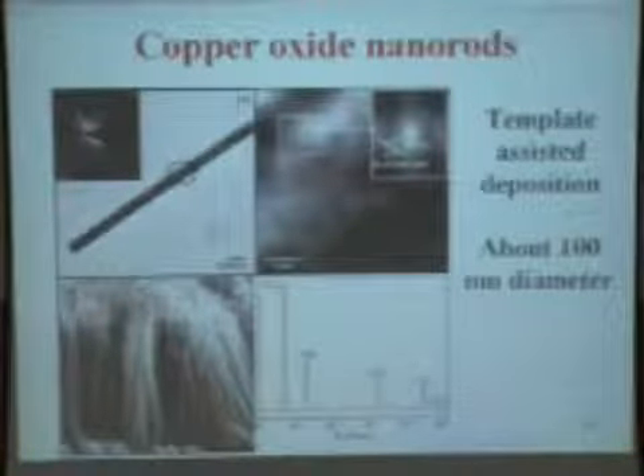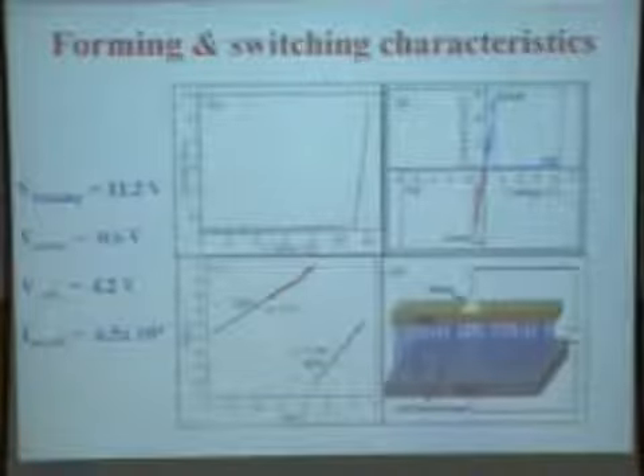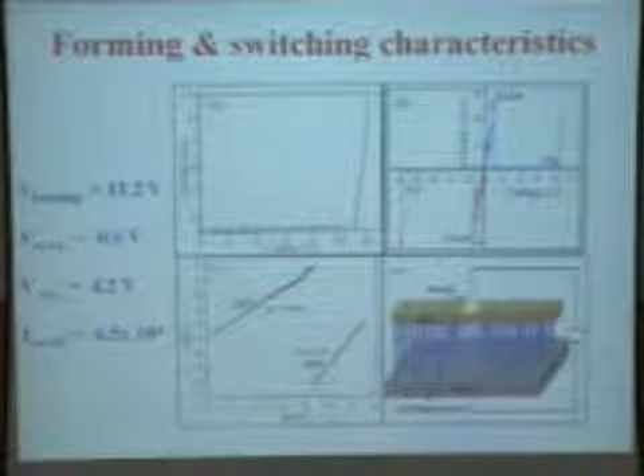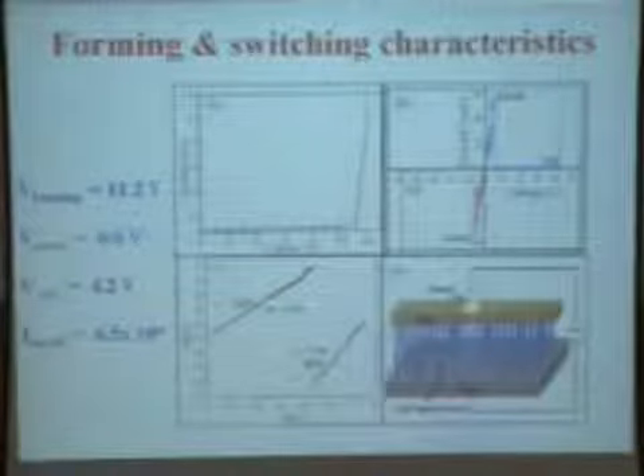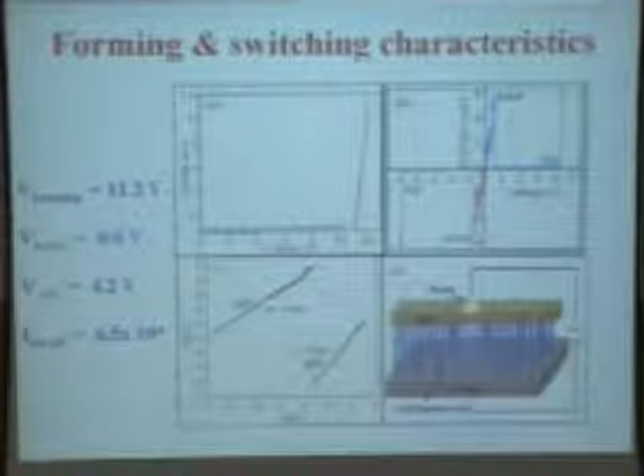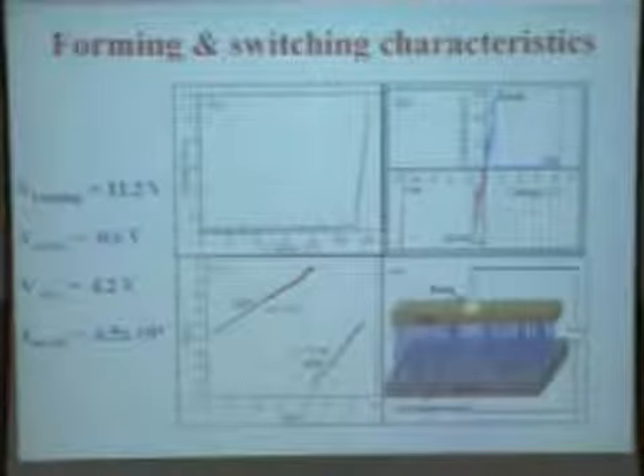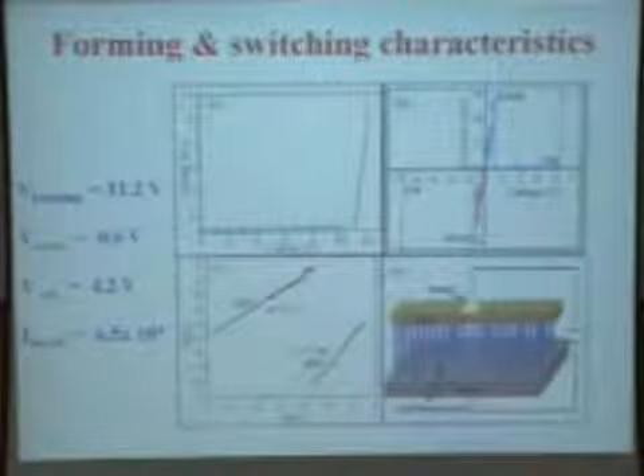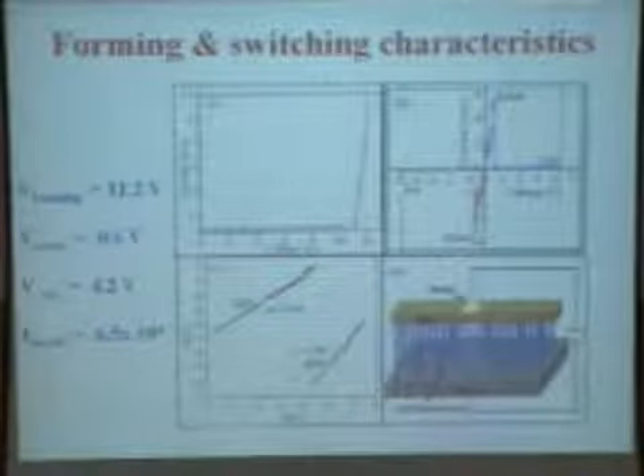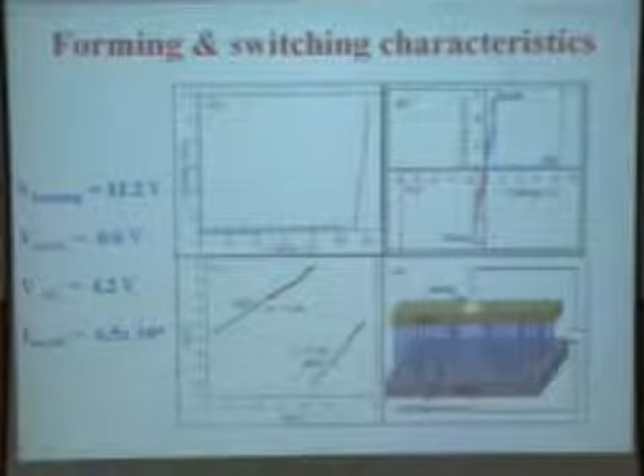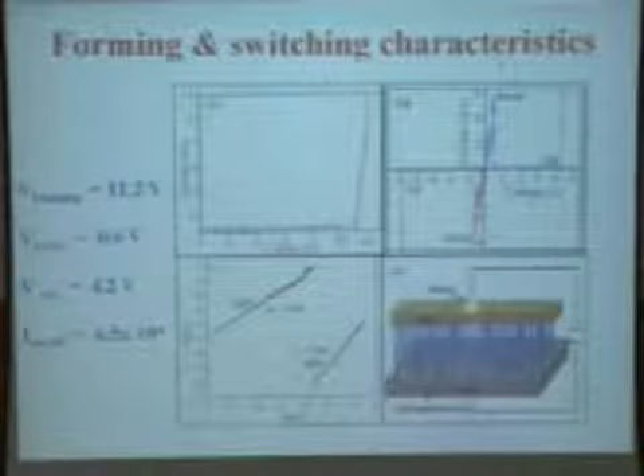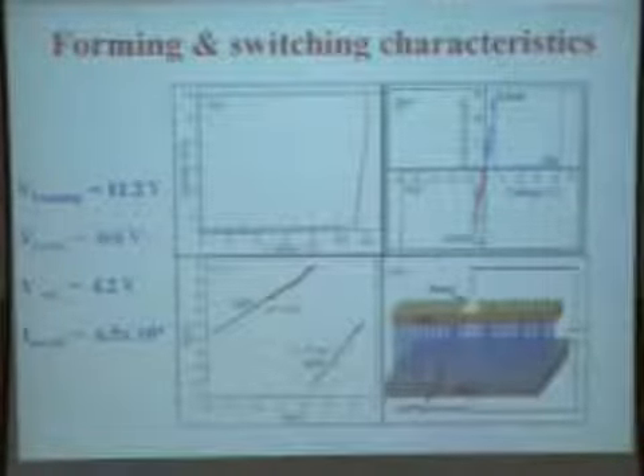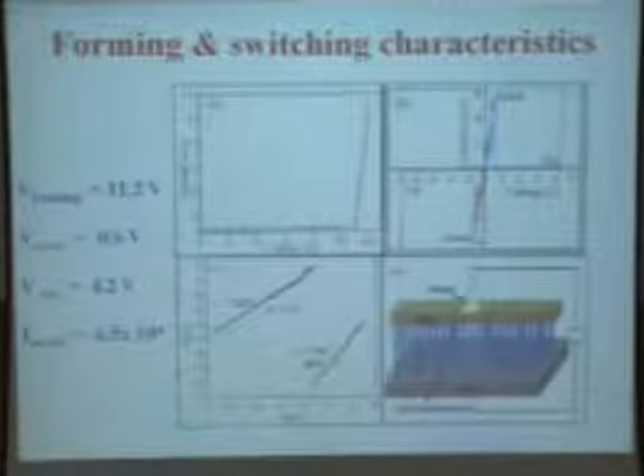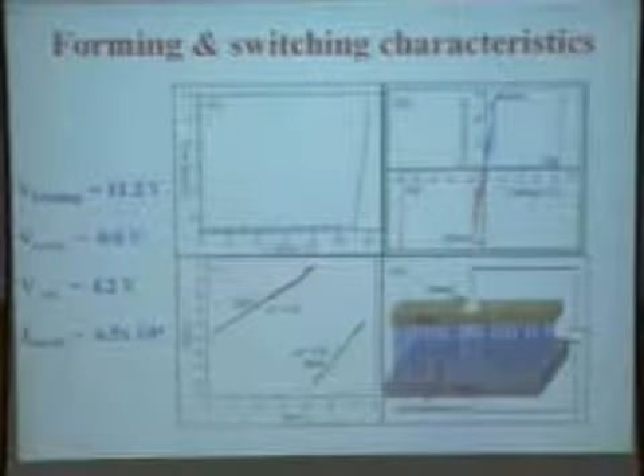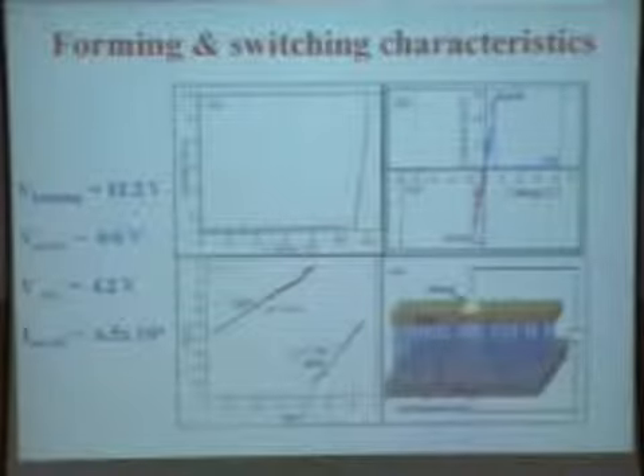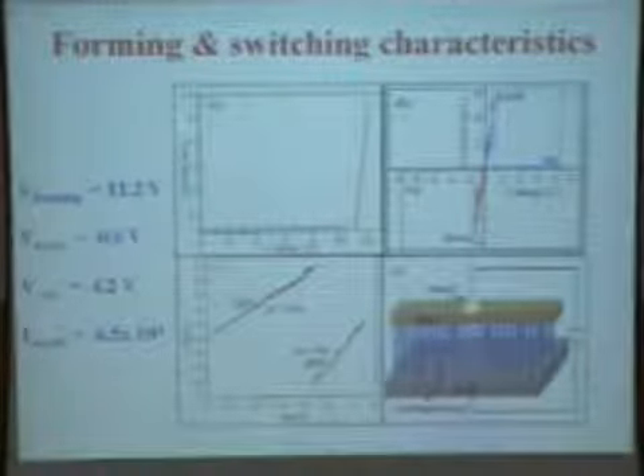So what we did, we had this kind of structure, then we made an insulating layer, then we opened it, filled in mercury, and made an electrical contact, and you can see that we could observe the electroforming process. This is the first step. You apply a voltage of around 11 volts, and the material goes to the low resistance state. Then you can see here, you are in the low resistance state. At this voltage, it comes back to the high resistance state. At this voltage, it goes back to the low resistance state. So you can switch between the low and high resistance states by applying voltage.